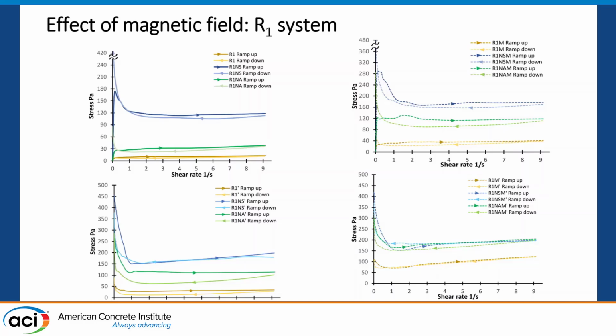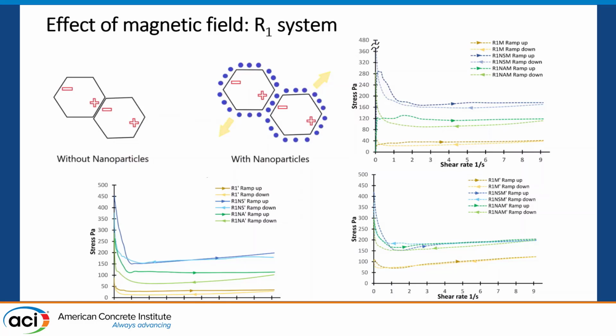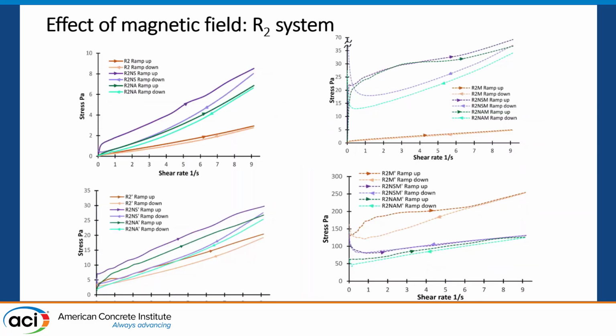And a reason for that is the nanoparticles we used actually were not magnetic. So when you have magnetic inclusions, basically magnetite, and I don't have fly ash here, the magnetite particles were surrounded by non-magnetic particles. They were actually preventing contact and building the chain. So basically, this is where non-magnetic particles may not interact well with magnetic particles. And so this is the reasoning why we like to see magnetic nanoparticles used in the system. Well, when we use a system with fly ash, I initially demonstrated that this system is not very suitable for 3D printing application, but you can see that the Newtonian response from the reference 50% fly ash system can be converted to Bingham response, and for systems with nanoparticles the response was really enhanced.